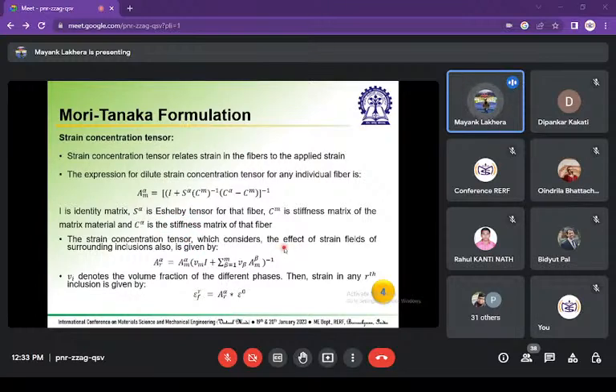But if I want to study the effect of other fibers on that particular fiber, then this is given by the strain concentration tensor, which is given by this. This AM is again the dilute concentration tensor, and VM is the volume fraction of the matrix. I is the identity matrix, and V beta is the volume fraction of the particular fiber for which we are calculating the strain concentration tensor. And again, AM is the dilute strain concentration tensor. In this way, we can find out the effect of the other inclusions on that particular inclusion also.